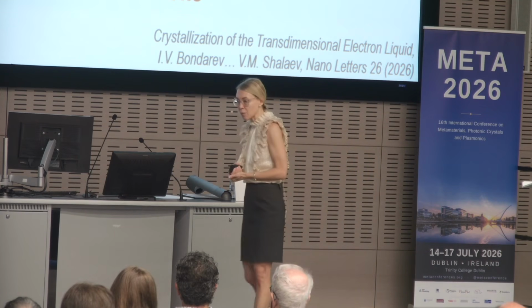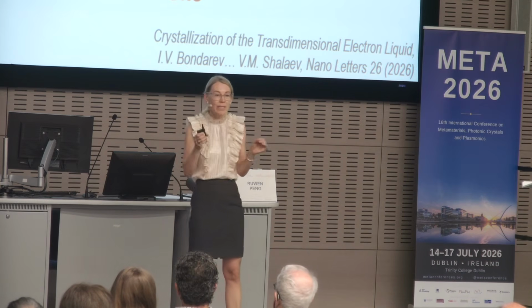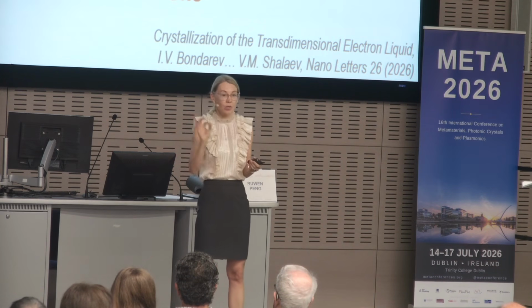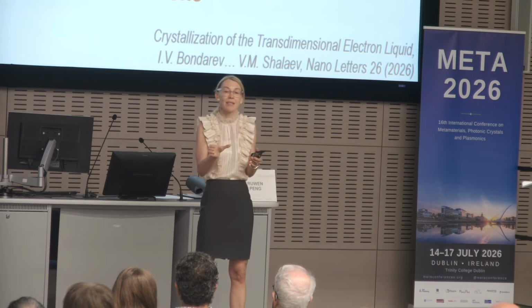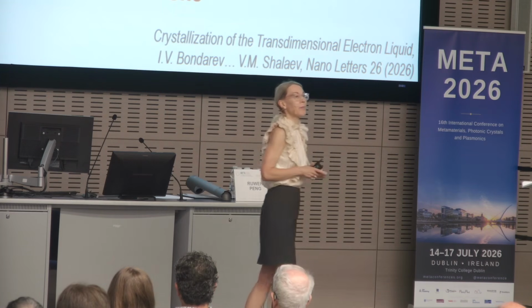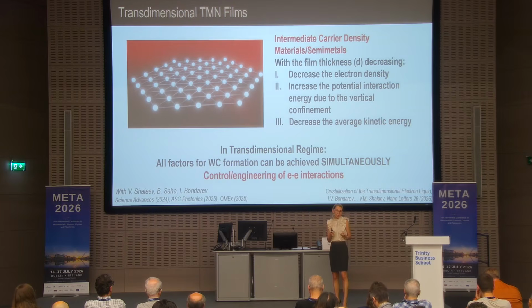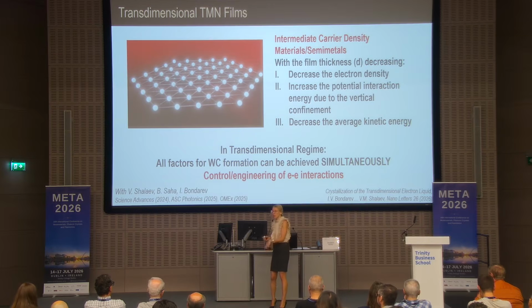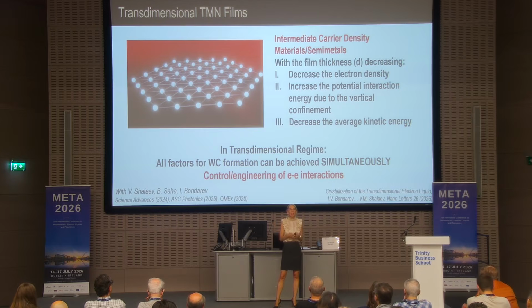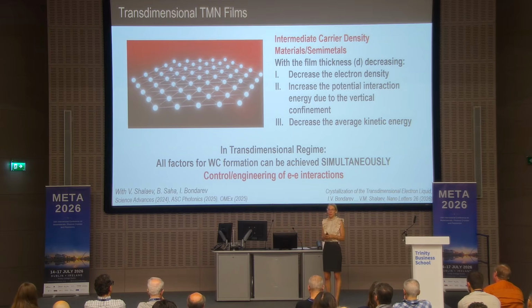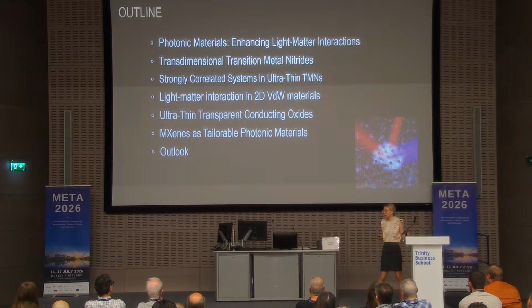because in these materials, and let me call them intermediate carrier density materials, you really reside between semiconductors, 2D films, and metals, because you have access to this great tunability and tailorability of your carrier concentration, which simply can be changed by choosing the right semi-metal and changing the thickness. And then you can control the quality of material, substrate, superstrate, and you will actually find yourself covering pretty much the unexplored areas of this phase diagram that indicates where Wigner crystallization can be observed. So, an interesting platform for exploration.